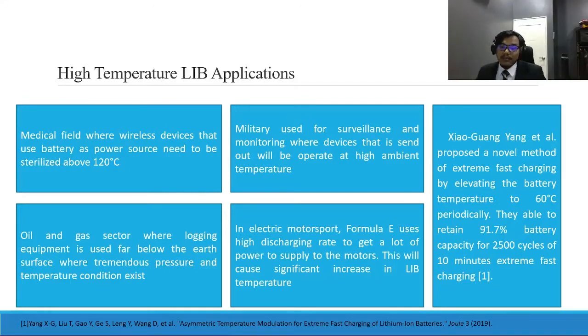In electric motorsport, Formula E uses high discharging rate to get a lot of power to supply to the motors. This will cause significant increase in lithium-ion battery temperature. And in recent studies carried out by Xiao-Guang Yang et al., they proposed a novel method of extreme fast charging by elevating the battery temperature to 60 degrees Celsius periodically. They are able to retain 91.7% battery capacity for 2,500 cycles of 10-minute extreme fast charging. 10-minute charging is quite fast for a large battery pack.